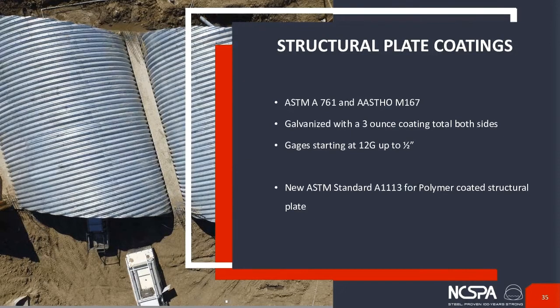So we've talked about corrugated metal pipe, and wanted to also mention that we, as an industry, manufacture a product called structural plate, and it's for larger structures. It's a different corrugation, and it comes in big sections that are bolted together in the field. But that product comes with a hot dip galvanized coating, or it can come with a recently developed, you'll see the bottom bullet there, a polymer coated structural plate, not aluminized. It can't come in that product form, but it does come in hot dip galvanized, and it is a thicker galvanized coating than standard corrugated metal pipe coil. And then, like I said, this more recently developed polymer coating on the structural plate accomplishes the same thing as the trench coat product.